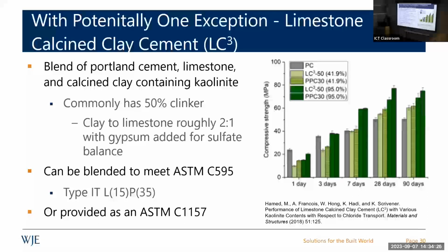It's becoming a viable product where they're taking about 50% clinker. So we're not getting rid of clinker, but they're blending with impure kaolinitic clays and limestone at higher addition rates. And the papers are worth reading. It's worth investigating. This work is showing great promise and is scalable because these low quality kaolinitic clays are available pretty much everywhere. So from a scalability perspective, from a raw material perspective, they're very much available.